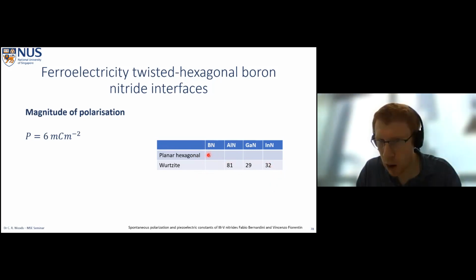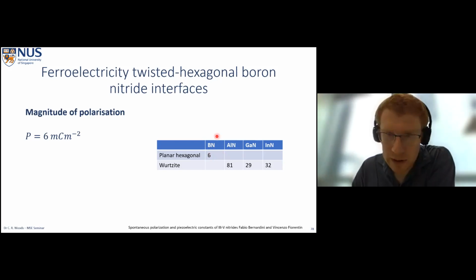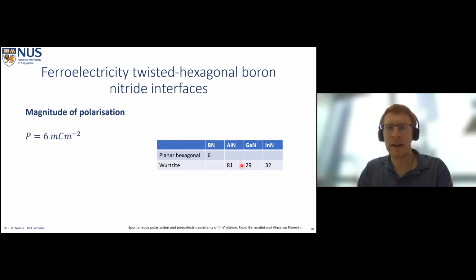But we can understand why it's actually quite a big polarization in our case by just thinking about the bonding, because this is sp2 bonding, whereas over here we should have sp3 bonding, which increases the likelihood of the electrons being found on the non-nitride atom, whereas here we would have quite a large polar nature between our boron and nitrogen. So this is actually quite a large polarization for what we would expect, even though in absolute terms it's smaller than these others.